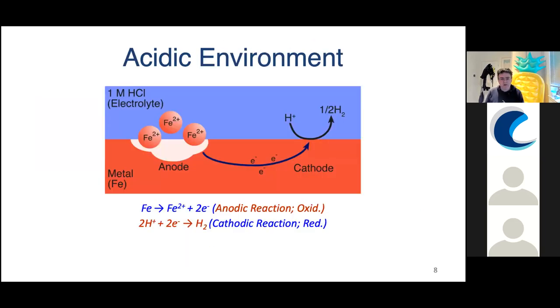So just to start with, just to remind you what an acidic environment looks like in terms of electrochemistry. Here we have one molar hydrochloric acid, a strong acid, a low pH. The metal here is iron, or could be carbon steel, and we focus on carbon steel in this talk. And we have two parts of the corrosion. We have our anodic oxidation of the iron, Fe going to Fe2+. And at the cathode, in this case, the main reaction is reduction of protons to form hydrogen molecules.